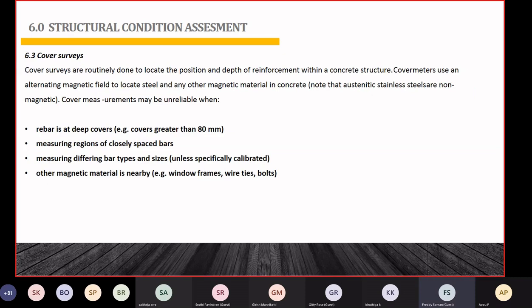Okay, cover survey. As I mentioned earlier, in the independent side also, we get all the readings of the depth at which the rebar is embedded in the concrete, that's the cover. Specifications vary; in some it is about 50 mm. In India, I'm not sure, because it depends on the exposure conditions. Some areas require 40 mm, some 50 mm, but in Oman the minimum should be 50 mm for whatever the conditions. We can also find regions of closely spaced bars, steel congestion, different bar types, sizes, and other magnetic materials nearby using cover surveys. Okay, so move on to the next slide, sir.